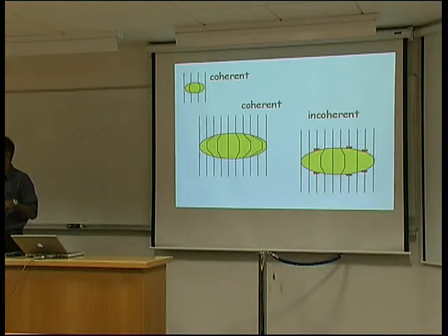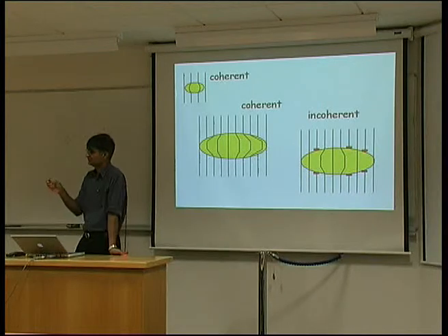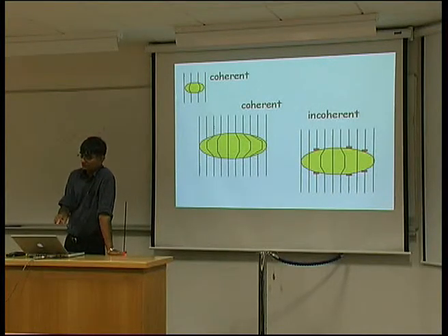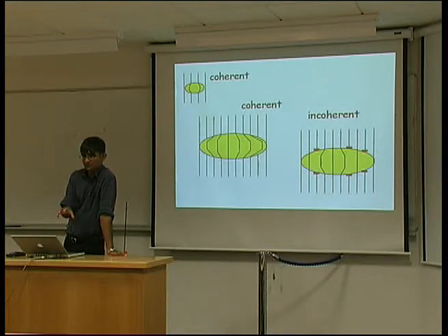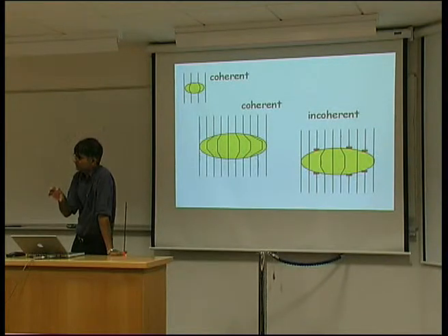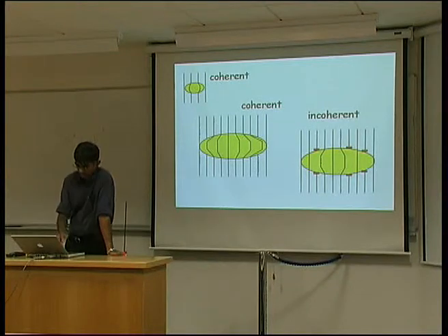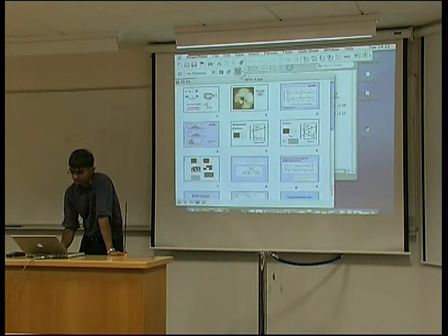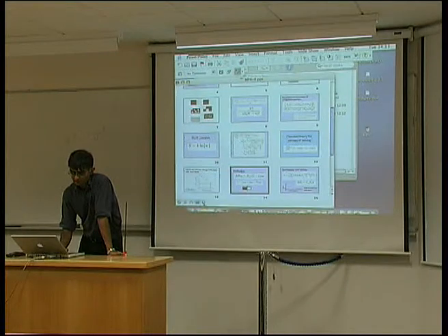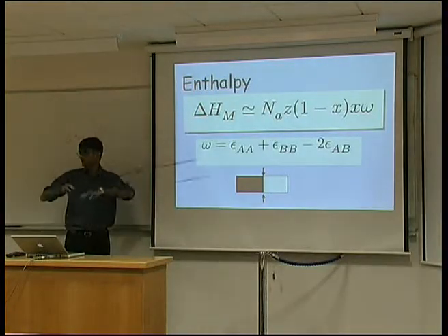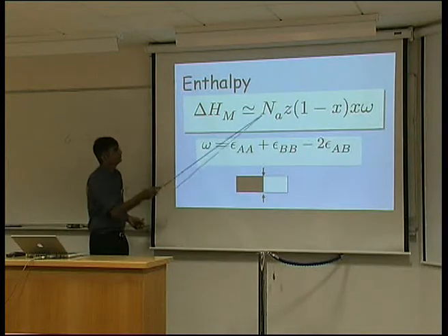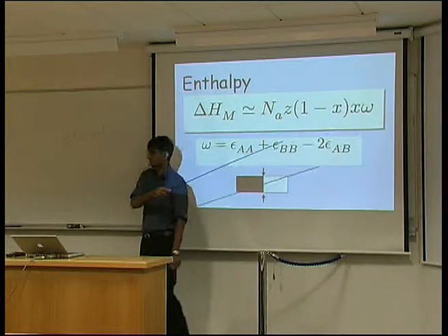But we've also done another component, which is the chemical component, because the yellow phase might have a different chemical composition from the matrix in which it precipitates, and even if they have perfect crystallographic matching, there's a discontinuity there. And that discontinuity we expressed slightly differently. So this is the enthalpy of mixing when we take two crystals and mix them up completely. So this is the change in binding energy and so forth.